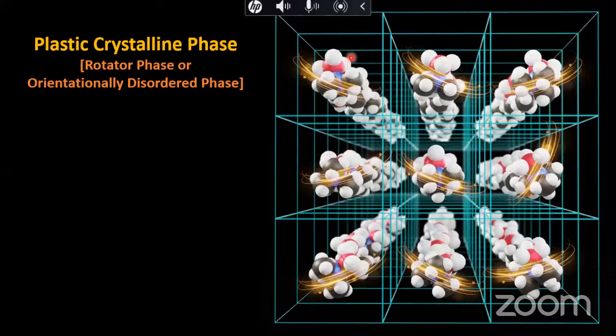when you call them plastic crystals, you actually have molecules which rotate in the solid state. That means you have crystals where molecules rotate along one or more axes. That is why these are called rotator phases or orientationally disordered phases. For example, if you look here, you have nicely packed molecules. They sit in their position, they don't move. You have a nice lattice, and it is highly ordered. But molecules sit in their position, and at their own position, the molecules rotate. That is why they have a dynamic disorder.